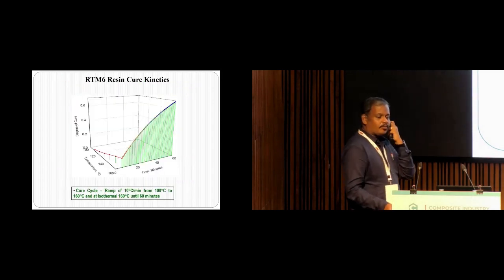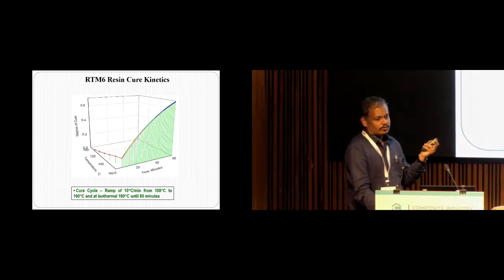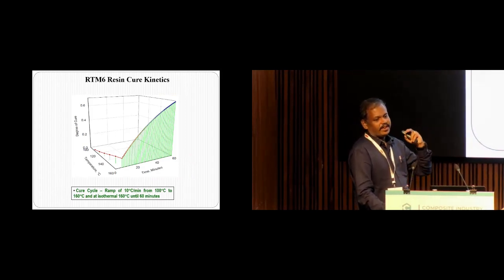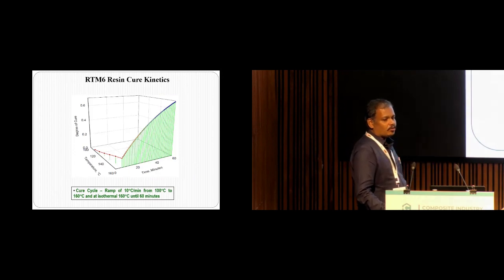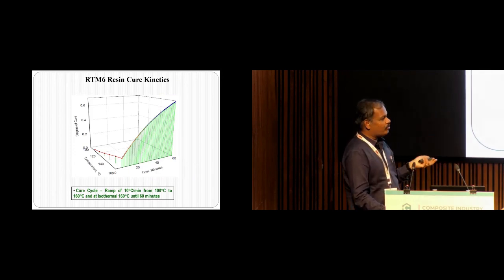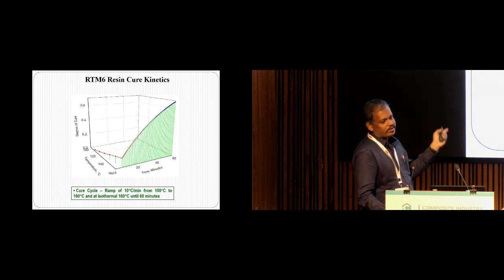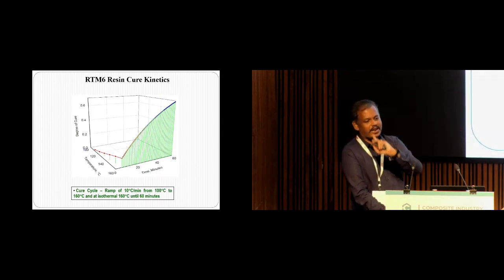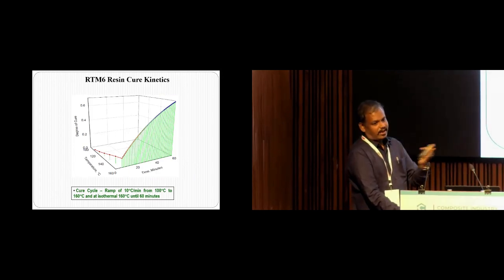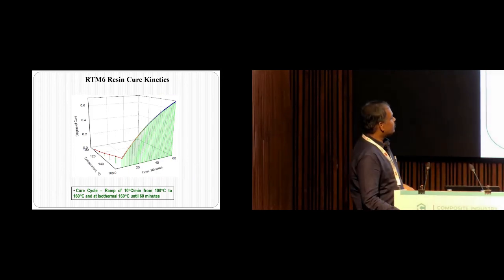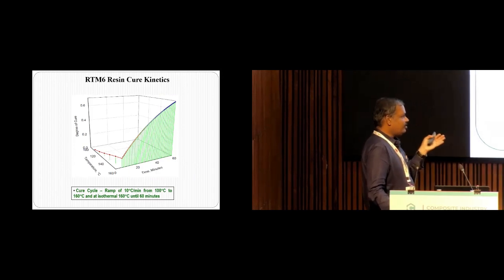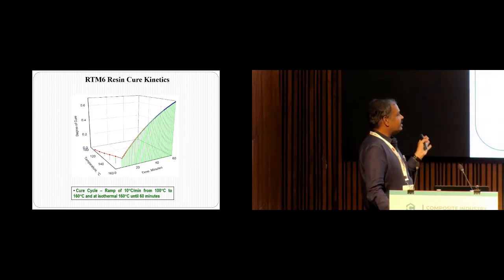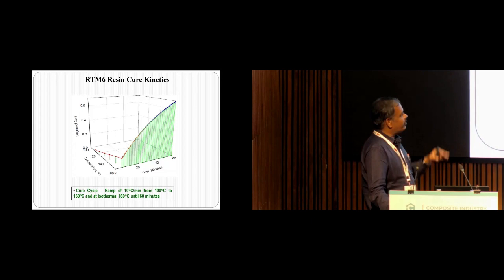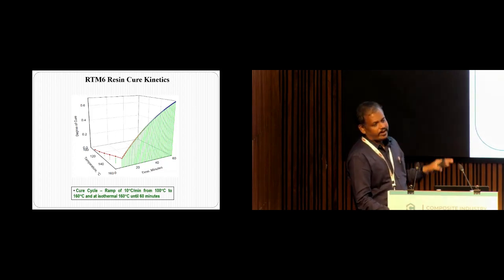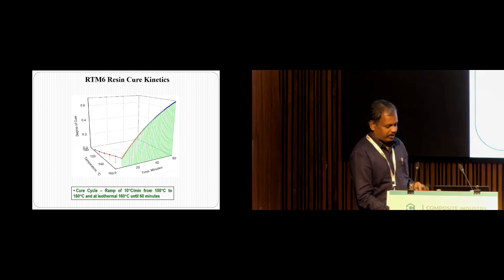If you know composite molding processes, there are two parts. One is the ramp. If I have to go to 160 degrees centigrade, you cannot go to 160 degrees straight away. You have to use a ramp from room temperature to 160 degrees centigrade, and then hold a platform at 160 degrees centigrade isothermally for a given time. Here we used a ramp of 10 degrees per minute from 100 to 160 degrees, and at the isothermal temperature it stays at 160 degrees for 1 hour. We keep this cure cycle and try to find out the cure of the composite laminate.